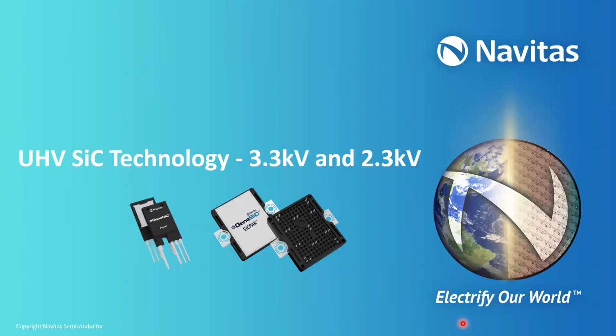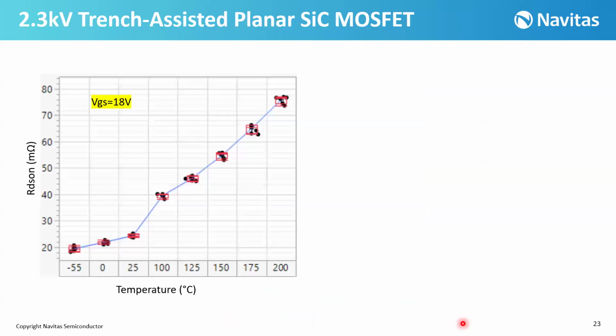Now let's look at the ultra high voltage silicon carbide technology, 3.3 kilovolt and 2.3 kilovolt. Here are the latest results that we achieved with 2.3 kilovolt, again utilizing trench-assisted planar silicon carbide MOSFETs. Here's the RDS on versus temperature from -55 to 200 degrees C with a VGS of 18 volt. And obviously, by increasing the temperature, the RDS on increases. At room temperature, we have an RDS on around 23 to 24 milliohm.